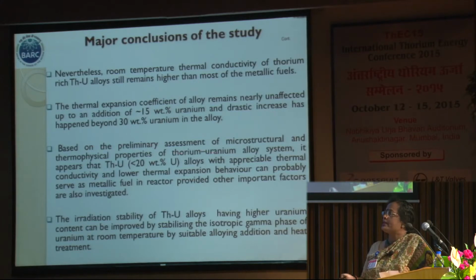Based on the preliminary assessment of the microstructure and thermophysical properties of the thorium-uranium alloy system, it appears that thorium-uranium alloys with less than 20% uranium, with appreciable thermal conductivity and lower thermal expansion behavior, can probably serve as metallic fuel in reactors, provided other important factors are also investigated.